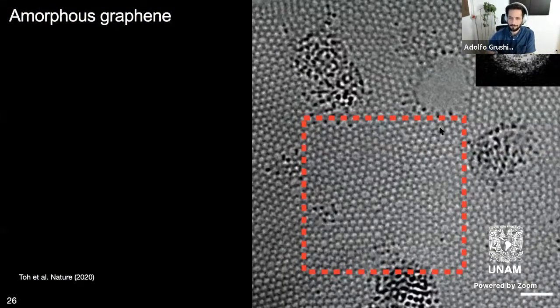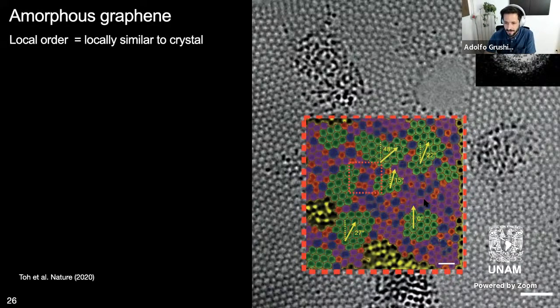If you take a snapshot, an image of amorphous graphene in transmission electron microscopy, you'll see that the local order is actually very similar to the crystal, meaning carbon is still carbon, so it will form three bonds. And if you color code it as the authors did, you see patches of hexagons like in normal graphene, which are maybe oriented differently. Then you see pentagons in red and heptagons and other types of polygons in blue, and maybe more isolated hexagons in purple. So you have all kinds of polygons around this little patch that I highlighted here. But nonetheless, most of these carbon atoms are coordinated with three neighbors, because carbon-carbon bonding in the plane wants to form three neighbors.